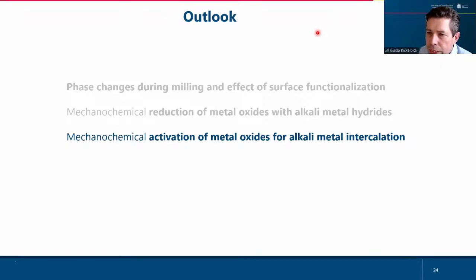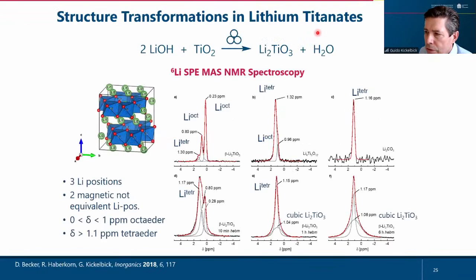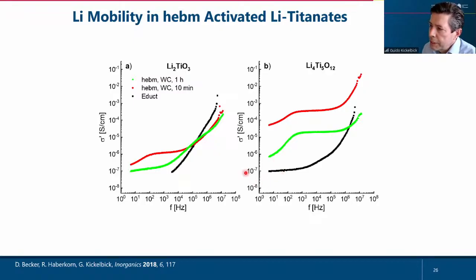I just want to show you that this lithium metal oxide formation is also interesting for applications. Here you see the formation of lithium titanate in the ball mill from lithium hydroxide and titania. Again, we proved by solid state NMR that in this case, not only the usual voids are addressed by the lithium, which you would expect under high temperature conditions, but also other voids, like the tetrahedral voids in the lattice.